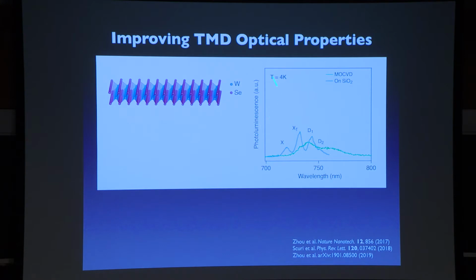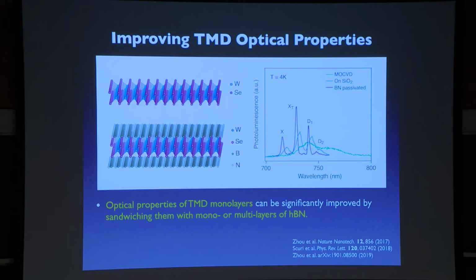If you somehow generate these atomically thin semiconductors and measure the optical properties, then oftentimes what you get are these broad-looking, kind of featureless peaks. If you get the best CVD grown samples and measure the spectrum, they look like this. And if you get the single crystal and cleave it using Scotch tape and then measure the spectrum, they look like this. When I say that we want to make these material properties as clean as possible and make as clean a canvas as possible, what I mean is the following. I want to make these features as sharp as possible, and that gives you a measure of the quality of the materials.